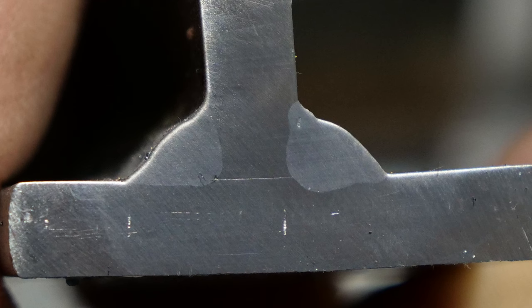This weld, I didn't shoot the face of it, but there was a couple very small pieces of porosity that you could see from the surface. Very typical for flux core. Had I been able to run higher wire feed speed, like I really should have to be welding this, I think that would have solved it somewhat. But it's hard to say because I can't run my actual amperage.